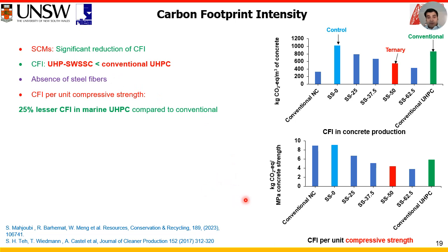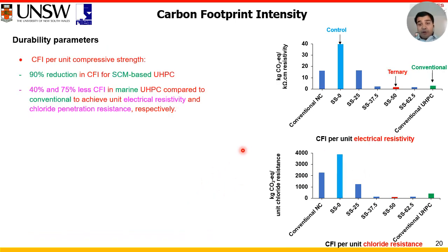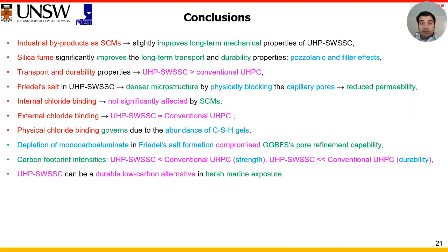Now when we compare the carbon intensity to produce per megapascal concrete strength, we saw some impressive results: with the utilization of SCMs, the carbon footprint per megapascal of strength will reduce. If we compare the carbon footprint per unit durability, the results are amazing. We can see that the ternary mixes can save up to 90% of carbon dioxide production compared to the control mix, and 40 to 75% less carbon footprint intensity compared to the conventional UHPC mix.